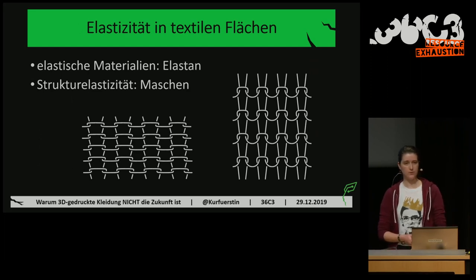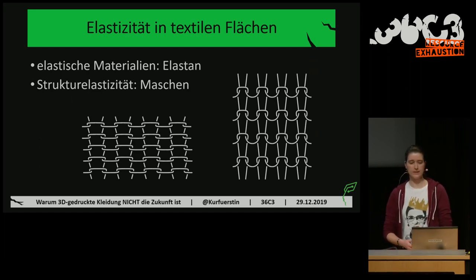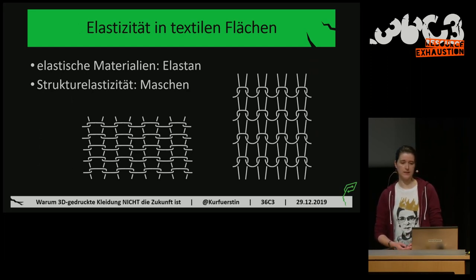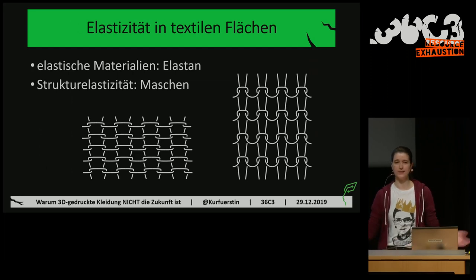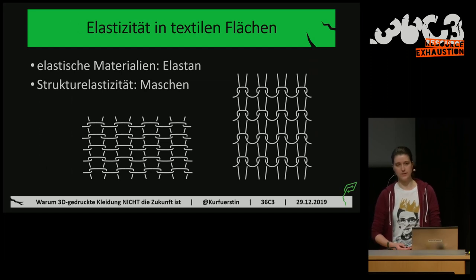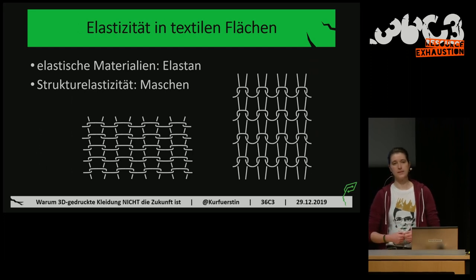If you look at textile surfaces, like the ones that we wear every day, they implement the elasticity in two ways. The material itself may be elastic. It's usually called elastan. It's awesome. You can stretch it by 300% and it'll spring back, and it's used in many, many pieces of clothing. A usual mix ratio is 98% cotton, 2% elastan. And those 2% are enough for the shirt to be movable enough to get in there. It can be very tight, but it won't deform after wear.